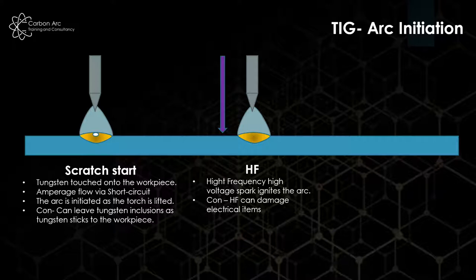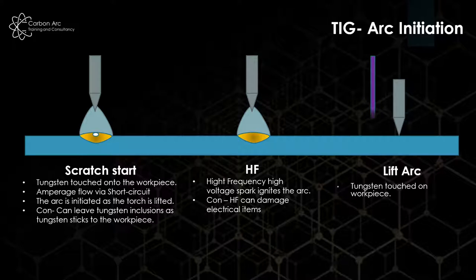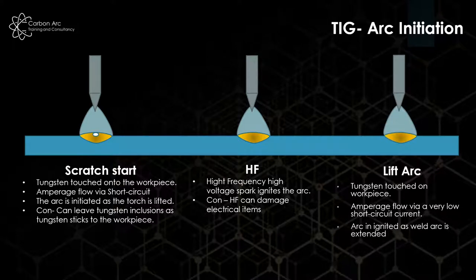The other is lift start, where like scratch we move the unit down to touch the workpiece, but instead of full amperage we see very low amperage flow through the tungsten into the job. As we pull back, the system detects the increase in resistance through the arc and the arc is ignited through the electrical system. We've got the benefits of not having arcs sticking and tungsten inclusions, and we don't have the high frequency danger, but the systems are a lot more expensive.